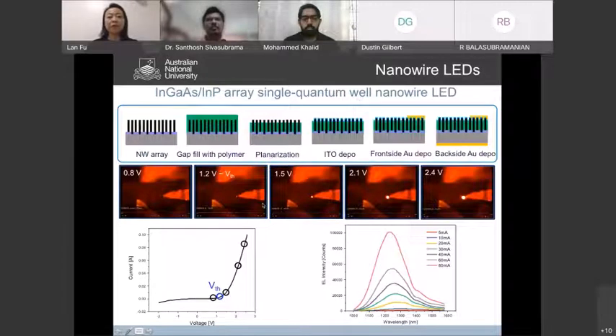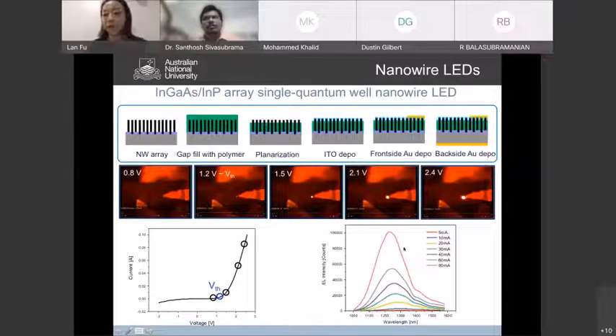And then, of course, if we planarize the whole device and make contacts on the top and back of the sample, we can also achieve an array LED from the material. And this is the infrared imaging showing the light emitting from our single quantum well array LED structure. So that's just showing that nanowires can make really quite nice LEDs.